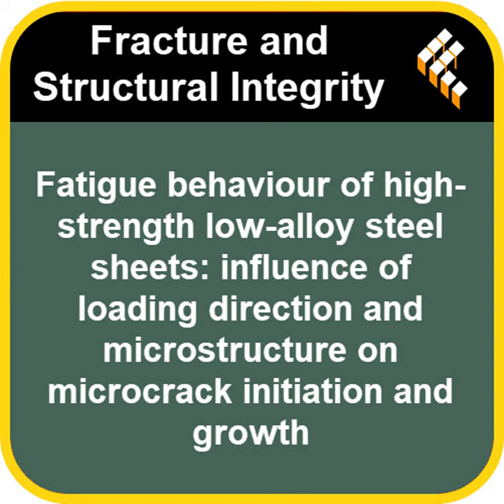DD was interesting. At low strains, it behaved much like RD, quite good fatigue life. But at higher strains, its fatigue life dropped and became closer to the poor performance of TD. And you mentioned something odd about that Coffin-Manson plot for TD and DD. It wasn't a straight line.